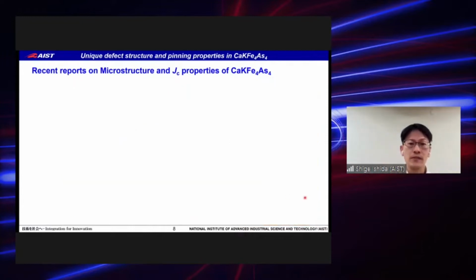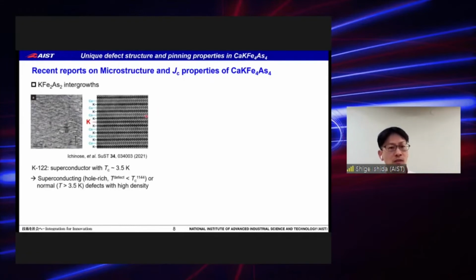Finally, let me briefly introduce recent reports on microstructure and JC properties in calcium potassium 1144. We first observed calcium 122 intergrowths, while it has been revealed that potassium 122 intergrowths also exist in this material. Potassium 122 intergrowths are thought to be hole-rich, and they can be superconducting or normal defects depending on thickness and temperature. As in the case of calcium 122, they are also expected to act as efficient pinning centers.